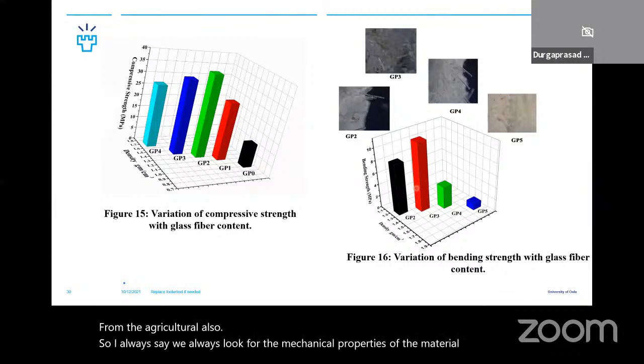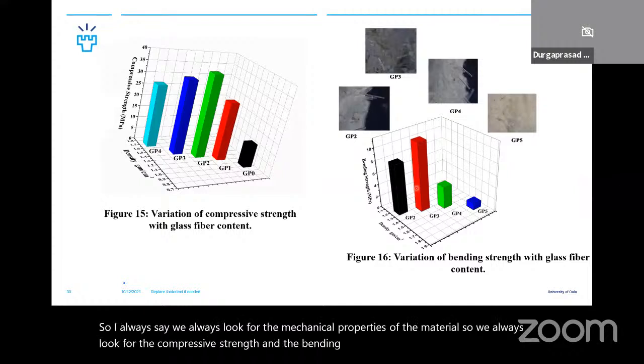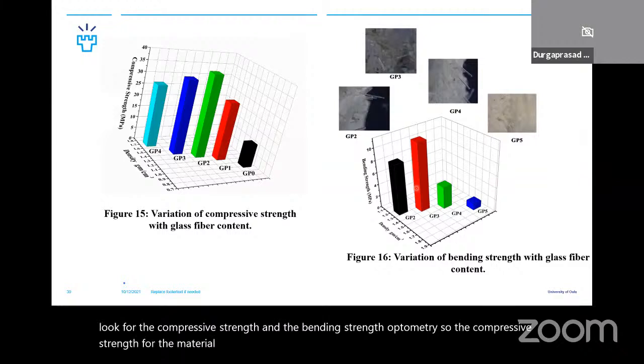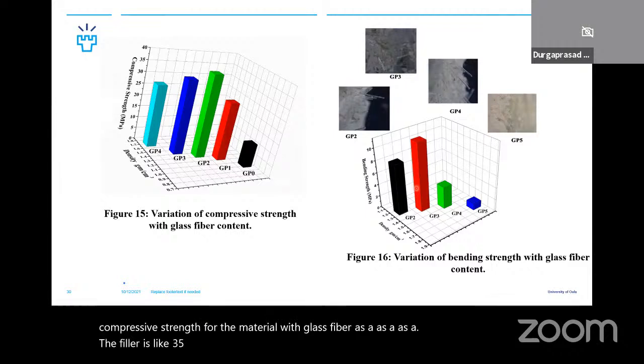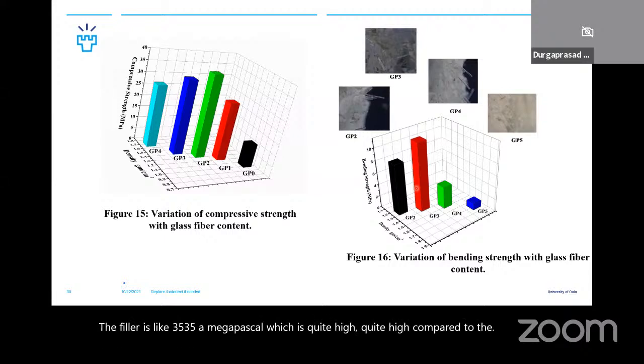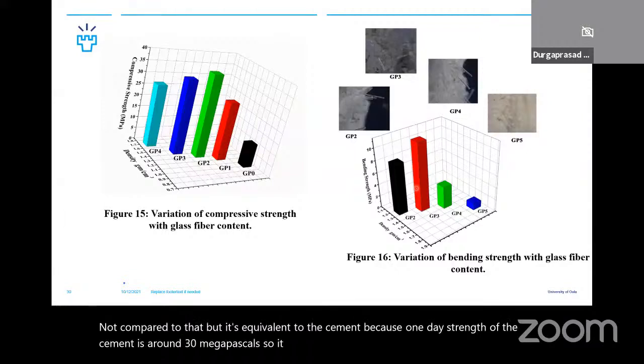I always say we look for the mechanical properties of the material. So we always look for the compressive strength and the bending strength of the material. The compressive strength for the material with glass fiber as the filler is 35 megapascal, which is equivalent to the cement, because the 1 day strength of the cement is around 30 megapascal. So it has a compressive strength of 35 megapascal.